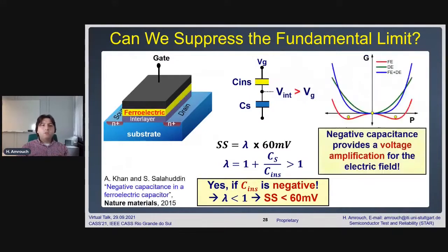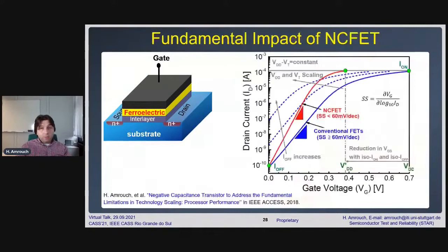Interestingly, it has been demonstrated that the ferroelectric material, under certain circumstances and certain capacitance matching, can exhibit a negative capacitance effect. That's amazingly important because instead of a voltage drop, as we used to have in any two capacitances in series, we have kind of a voltage amplification. As a result of that, we can achieve the same on current of our transistor, but at much lower voltage, as in this analysis that we have done at the 7 nanometer FinFET technology.